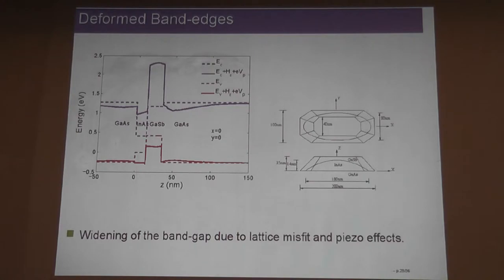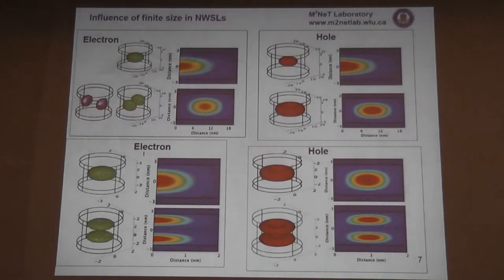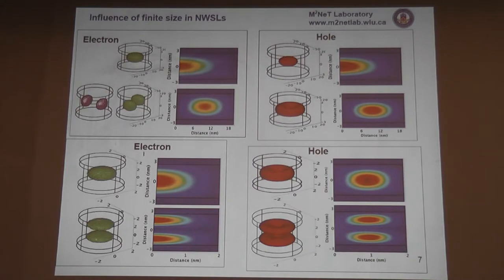Having developed this model — a couple of models which contain twelve partial differential equations, which you solve iteratively between the Maxwell plus elasticity equations, which you fit into your Hamiltonian for eight-band structure calculation models — based on that you could analyze a number of effects which are not possible without accounting for coupling. For example, in superlattices, many assumptions in the literature consider the structure as one-dimensional, but finite-size effects are important, and this model allows you to quantify them in nanowire superlattices.